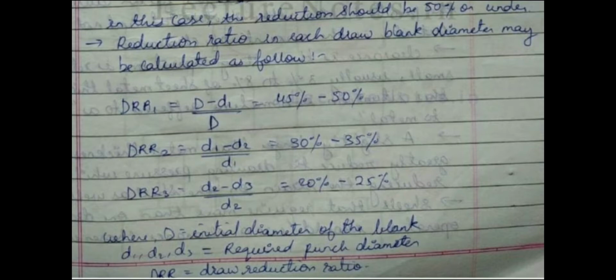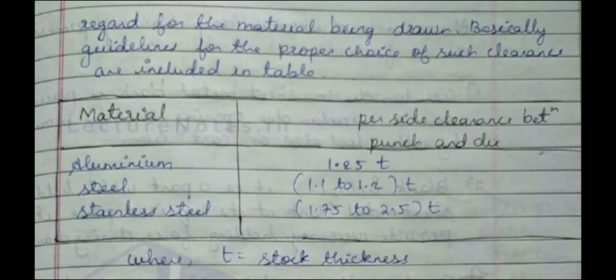Basically, guidelines for proper choice of such clearance are included in a table. So for different materials, different clearance is chosen. For aluminium, the clearance is 1.25 T. For steel, it is 1.1 to 1.2 T. For stainless steel, 1.75 to 2.5 T, where T is the stock thickness or sheet metal thickness. Okay, so this is about drawing clearance. Then redrawing limits, then reduction ratios, and metal flow in drawing operation we discussed.